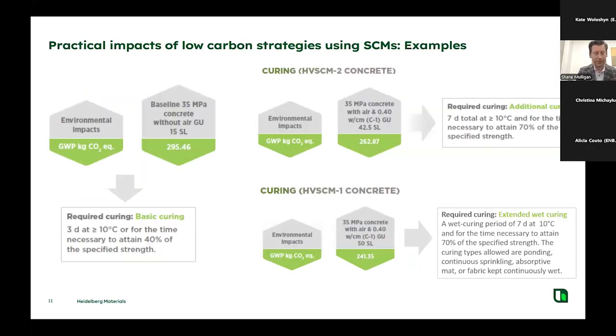Additionally, there's some on-site considerations that come into play when you're looking at higher levels of substitution rates. And these graphics come from CRMCA Low Carbon Concrete Guideline, where they look at different options for 35 MPa concrete, different substitution rates. And at 15%, that's pretty much the concrete that everybody's used to. There's no additional curing requirements on site.